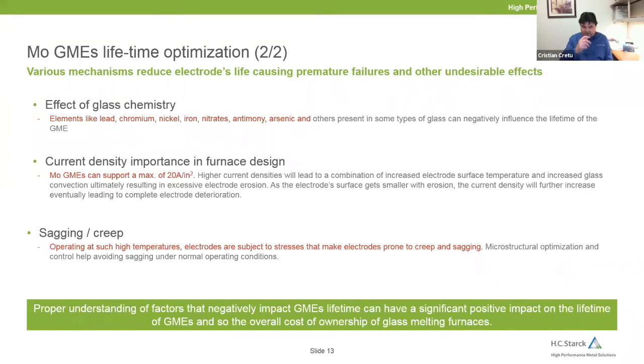Current density, also very important. One has to design for an electrical current density of somewhere around 10 amps per square inch. You can go a little higher. You can see here they can live as high as 20. But that will lead to 2 bad things: increased temperature at the surface of the electrode and increased convection in the glass, which both, one softens the glass, the other one erodes the glass.